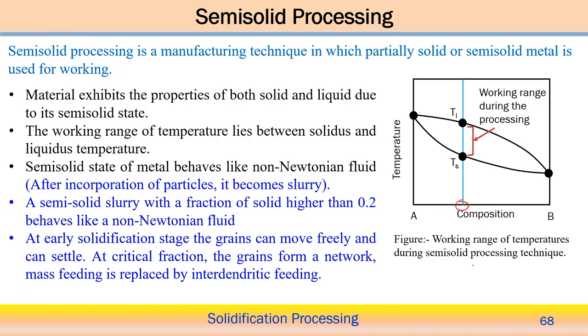But when you reach a certain critical fraction of the solidified component, it forms a kind of network, and in that case mass feeding is replaced by interdendritic feeding during the solidification process. I mean the grains form a network: initially a small grain can be created, and it can move freely without any obstacles. But after a certain time the primary dendritic arms and secondary dendritic arms create a network structure. When it creates this network structure, mass feeding of the liquid metal is difficult, rather interdendritic feeding is possible after a certain period of time. That is the way we can explain the solidification behavior of a particular metal.